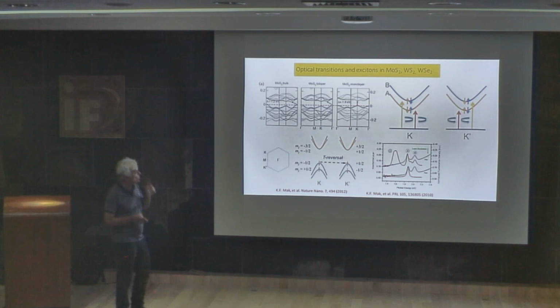I forgot to say one thing. In the case of those compounds, we have two excitons that we call the A exciton and the B exciton, because the A exciton involves a transition from this point to that point, and the B exciton from this point to that point. When you see the optical absorption spectrum of molybdenum disulfide, we can see this B exciton, and here is the A exciton. Okay, those are the most important features.